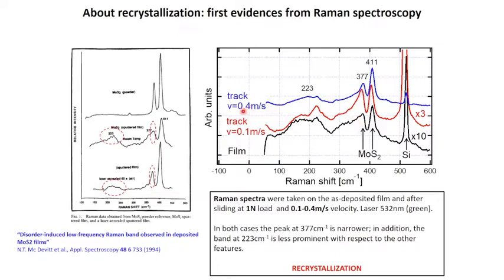And in the case of 0.4 meter per second, we also observe a decrease in the broad features related to 223. This is the first evidence of recrystallization of the coating, which probably has a role in the performances of the material.